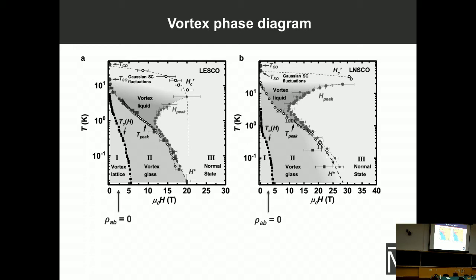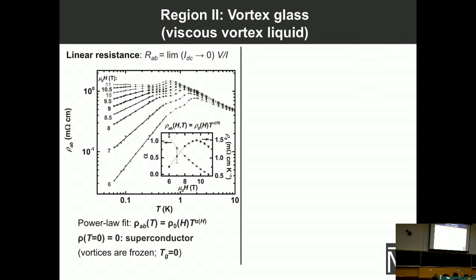So we see that this vortex solid is separated from the normal state, and I will show you the data later, by a wide range of fields, by a regime that we identify with the vortex glass. So what is the evidence for that? What we find in this regime that we call the vortex glass, first of all, is that the linear resistance phenomenologically is described best by a simple power law dependence. And this means that in the zero temperature limit, the resistivity will become 0. So the system will become a superconductor, which is what one expects when vortices freeze at zero temperature.